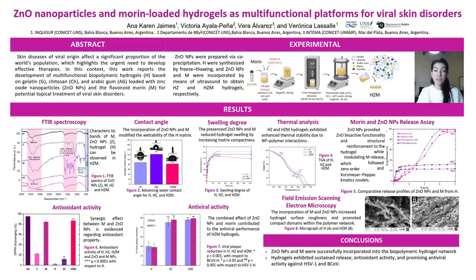Starting with Fourier transform infrared spectroscopy, characteristic bands corresponding to Morin, zinc oxide nanoparticles, and the hydrogel matrix were identified, confirming the successful incorporation of both bioactive compounds into the polymeric network. Regarding wettability, contact angle studies demonstrated that zinc oxide nanoparticles and Morin modify the surface properties of the hydrogels. In particular, Morin increases hydrophilicity due to the presence of hydroxyl groups capable of interacting with water molecules.